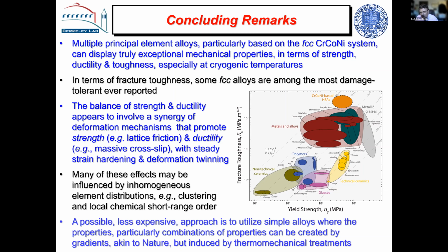When a dislocation moves on a planar slip band, it will destroy the local order behind it. We think that triggers twinning. We're trying to prove that now. And once it triggers twinning, and then presumably at a higher strain, you'll get the transformation to the hexagonal. And then the short range order tends to destabilize the formation of too much hexagonal.